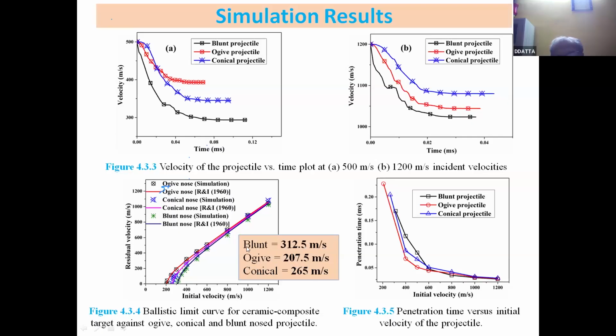It means that if we are using a blunt nose, perforation will take place after a velocity of 312.5 meter per second. Whereas for the ogive nose shape, it will perforate at 207.5 meter per second. So earlier we were discussing from the armor point of view, how we can make an armor strong. But if we want to make a study from nose shape point of view, projectile or the bullet point of view, then ogive nose performs the best because it can perforate the plate at the lowest speed, just because of its nose shape. That is why in all defense applications, ogive nose are used, and that is validated in our simulation.